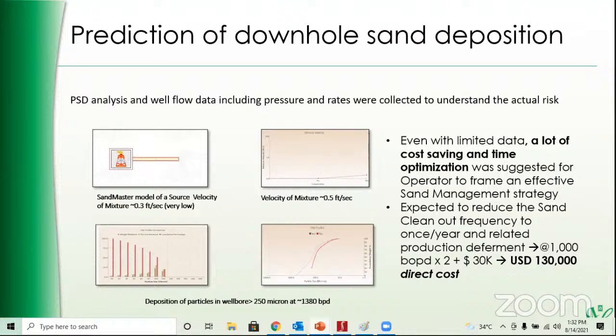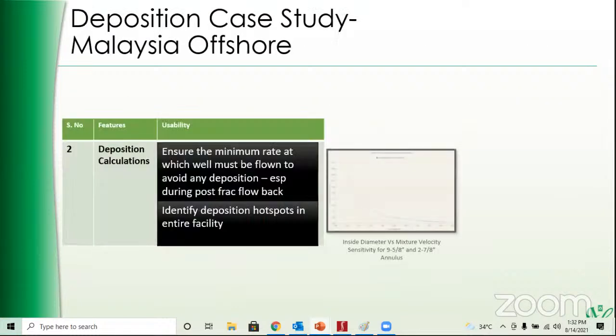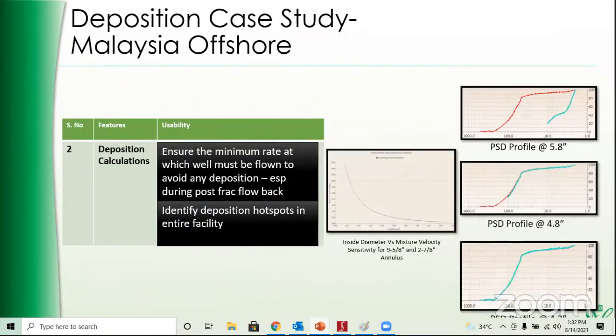So the software is not only giving you the idea of handling sand at surface, but also helps you at various places to optimize your production, optimize your revenue, and get more out of it. This is again Malaysian offshore. This is where they were flowing through the annulus with different inside diameters. They were flowing from a 9 5/8 and 2 7/8 inch annulus. 9 5/8 is your casing size, and 2 7/8 was the tubing size. Due to some reason, they had to flow via the annulus and then to the tubing.